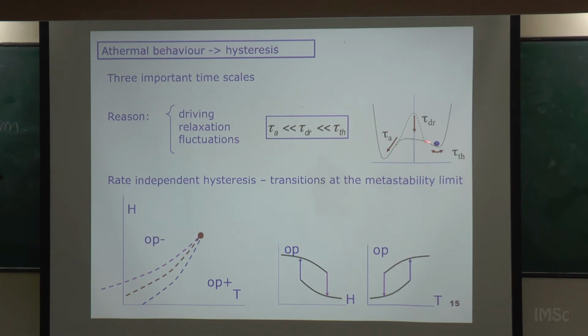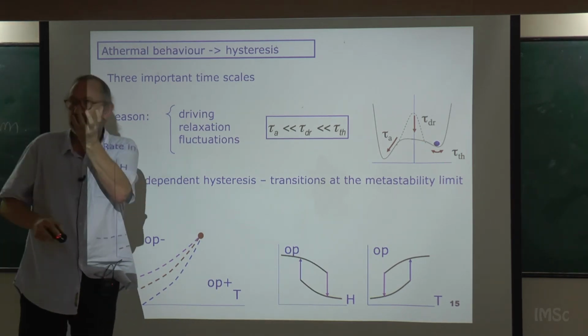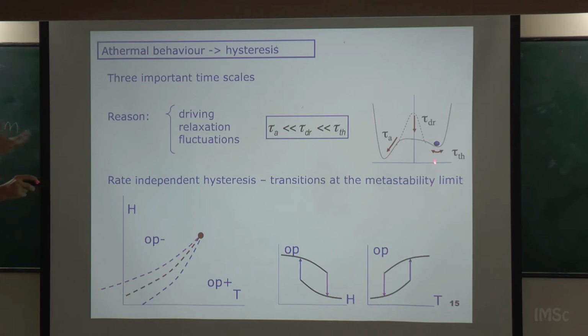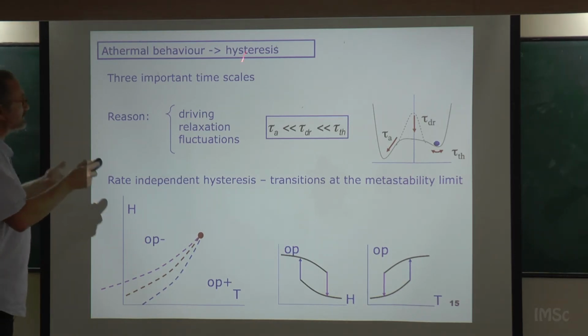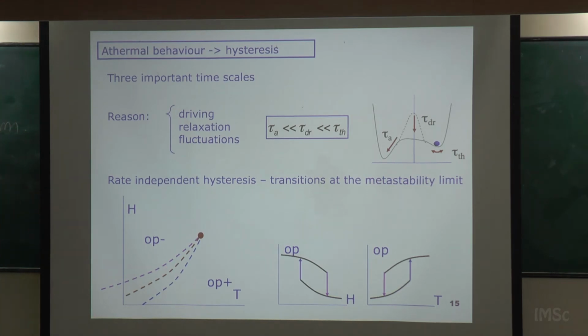We call it metastability because when the system is in this local minimum, this is not the global minimum, it's the local minimum, we say that the system is in a metastable state. The true stable state is not discovered until the barrier disappears. Okay, this is what we generally describe as an athermal behavior. So many first-order phase transitions in solids behave athermally. And this explains why we have two lines. But we have seen that there are not two, there are four lines. So we still need an explanation for the extension of the transition.